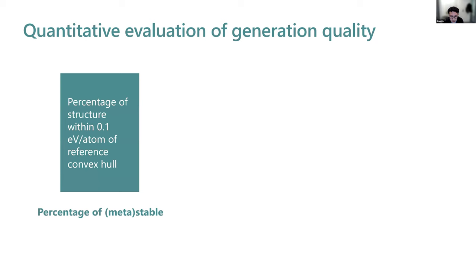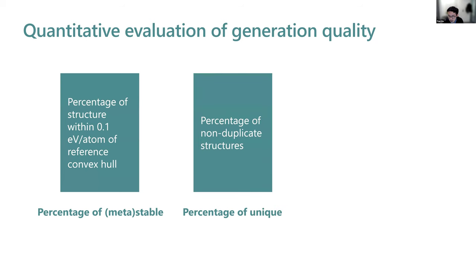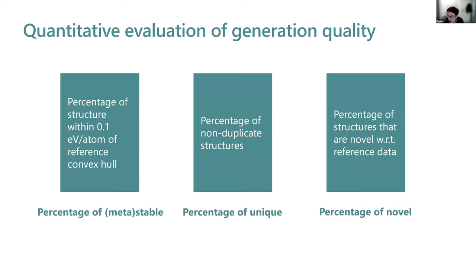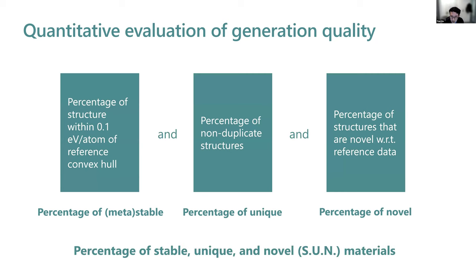First, there's the percentage of stable materials within 0.1 eV per atom. And then the second is the percentage of unique materials, because you hope to generate diverse materials. You don't want to generate a lot of duplicates. And the last one is the percentage of novel materials, because you don't want to regenerate structures that were in the training data. So then we combine all of them together. And so therefore our key metric is the percentage of stable, unique and novel structures, abbreviated as SUN materials, which is an interesting name that we came up with.